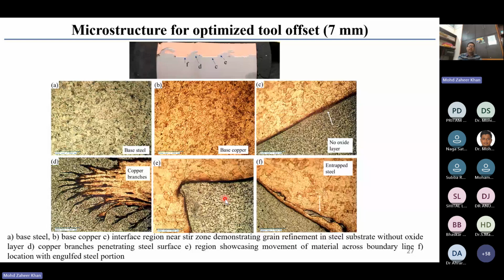So this can be clearly seen in this material. The process parameters were so ideally chosen that there was a very good intermixing that has taken place between the substrate material and the clad material, and the stirring of the material was really good.